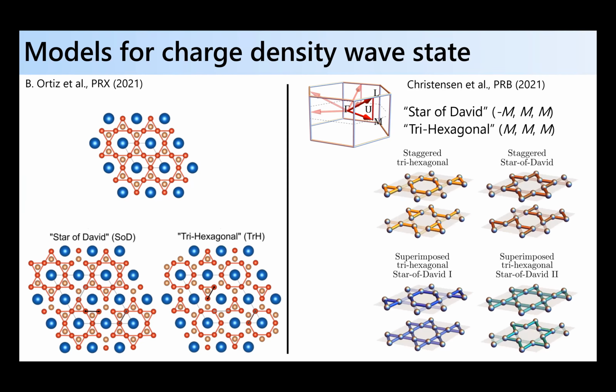But these are three-dimensional systems, and so if you start to think about the interlayer correlations, you can have a three-dimensional charge density wave state where you can, for instance, stagger the distortion of one plane relative to the other, meaning like if I have a trihexagonal distortion in one layer, I can shift it by half a unit cell relative to the next layer, and I can end up with a three-dimensional charge density wave state. Or you can imagine staggering the distortion types, trihexagonal, Star of David, for instance. You can generate some sort of three-dimensional structure by mixing in a distortion mode with this L-point symmetry.